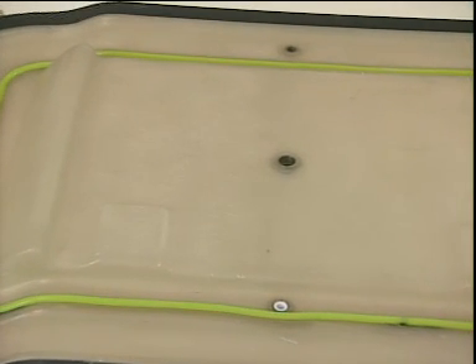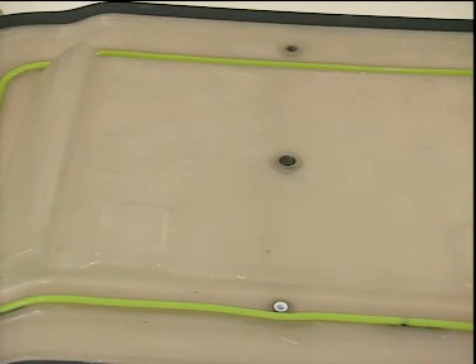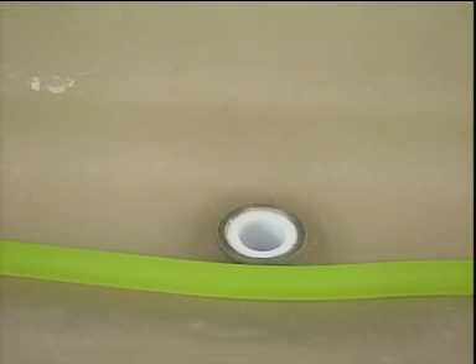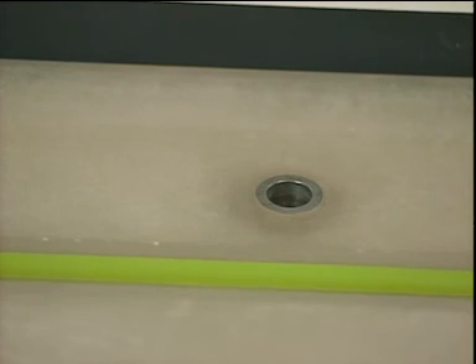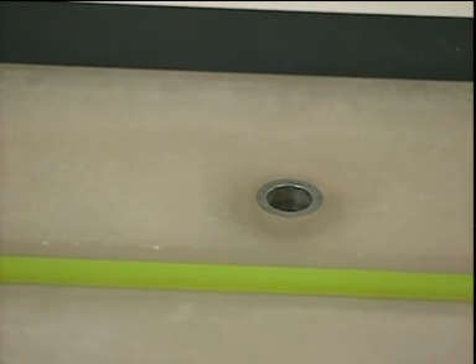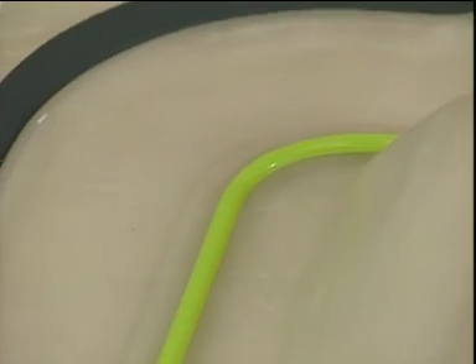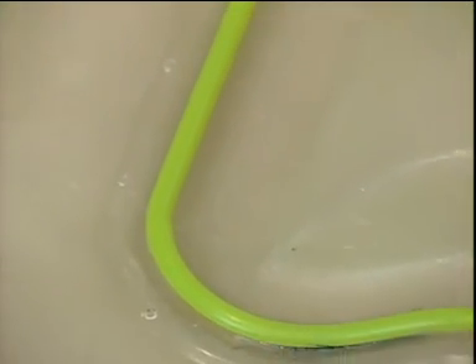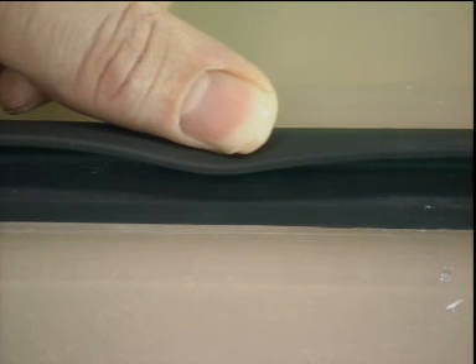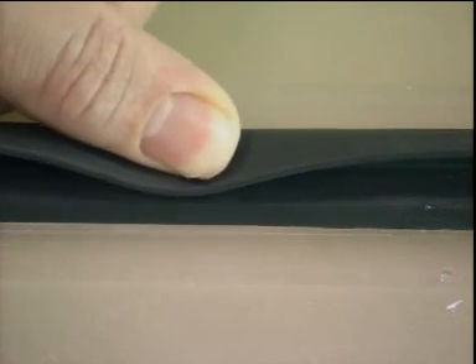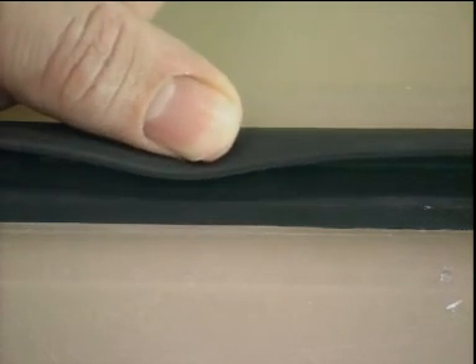A lightweight gel-coated GRP laminate using a more flexible resin system is ideal. Simple inserts can be used for the resin inlet, the central takeoff port, and the main vacuum clamping port between the double seal arrangement. The primary inner seal is of silicone rubber to ensure maximum resistance to styrene. The outer seal is of neoprene rubber and is extruded as a wing profile. This ensures easier mold closure and clamping.